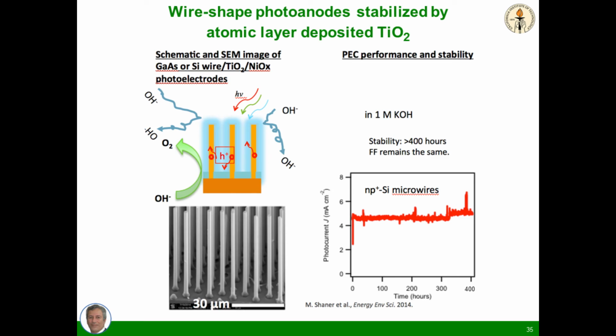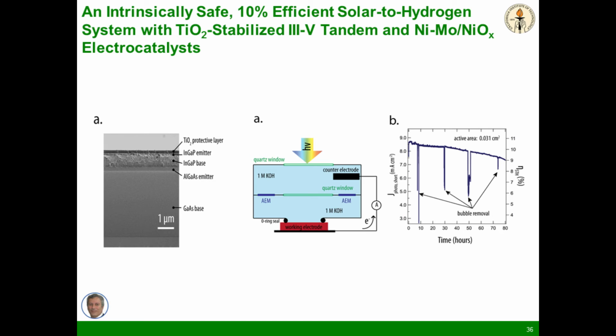We then showed that this could work in an entire system. We took a III-V based system that had a dual array of two emitters and one absorber. They were matched like D-cell batteries in series. We have the membrane, in this case not fully integrated, just side by side. We show we can pass hydroxide across the membrane. We show we can photoactively make this system, not co-evolve gases, but quantitatively form hydrogen and oxygen in a safe way at greater than 10% efficiency, stable for hundreds of hours.